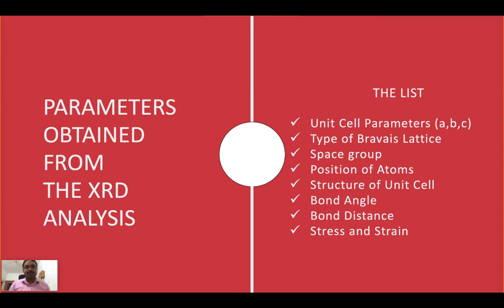Now we have come to a stage where we are going to see what parameters we have derived. Until now I have told you I can calculate the unit cell parameters A, B, C. Then I can know what type of Bravais lattice it is, whether cubic, tetragonal, rhombohedral, whatever it is. Then we are going to know the space group. If you know the space group, the position of atoms can be determined. Then the structure of the unit cell can be known. Then bond angle, bond distance, and stress and strain. All these things I can know from my X-ray diffraction analysis.